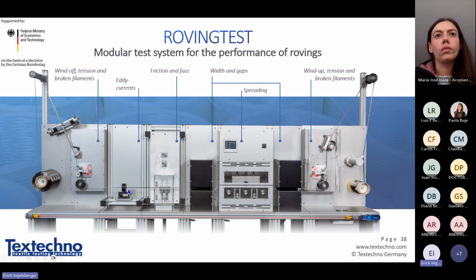Eddy current, this is used only on conductive rovings like carbon rovings. The parallelism, the alignment of the fibers or filaments, if they are all in the same direction, or if there is some error in fiber orientation, we can measure the friction and fuzz creation. I also will show you a video explaining this in detail. We have camera systems here before and after a spreading unit. This is to make a tape out of roving. So you make this roving and bring it to a tape. This is quite important and a common production step. So we measure the width before and after the spreading. And finally, of course, we have a wind up unit, which again measures broken filaments created during running of the yarn through this testing instrument. So it's a dynamic testing instrument measuring properties on the running roving.